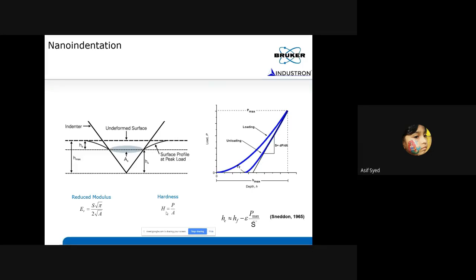So you can measure two properties. One is the plastic deformation property of the response of the material, which is hardness, and the elastic deformation of the material, which is the modulus. These are the two fundamental properties that you need to know to assess the mechanical strength of a material. Okay, this is something similar to when you do a tensile test. You know what the Young's modulus is, but yield stress is something similar to what you measure with hardness. In fact, 3 times yield stress is hardness of the material. So you can correlate to your old yield stress and Young's modulus using this indentation testing scheme.